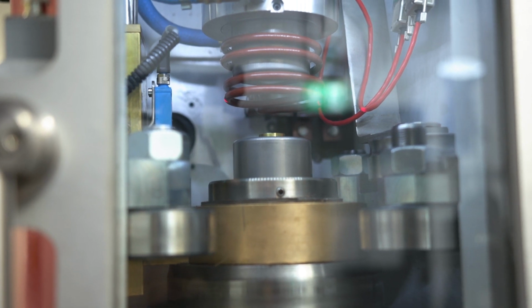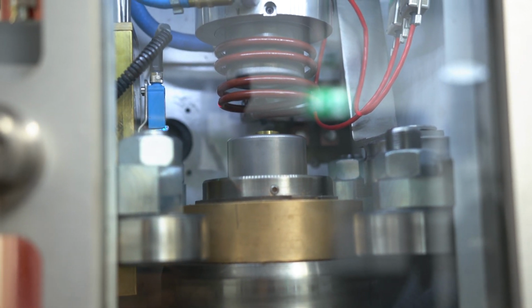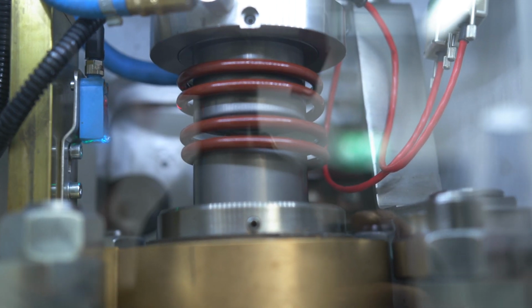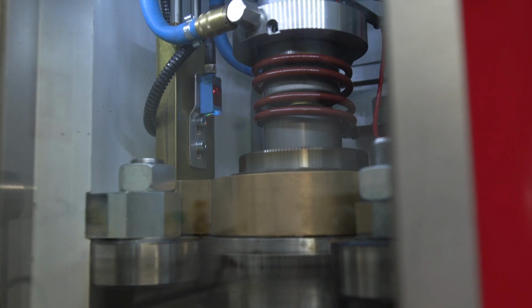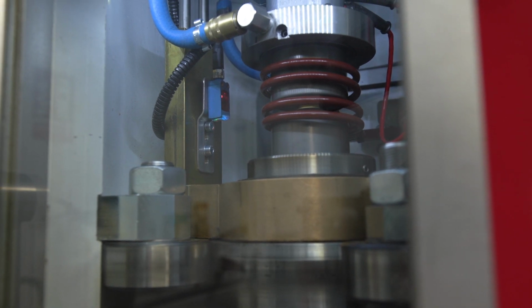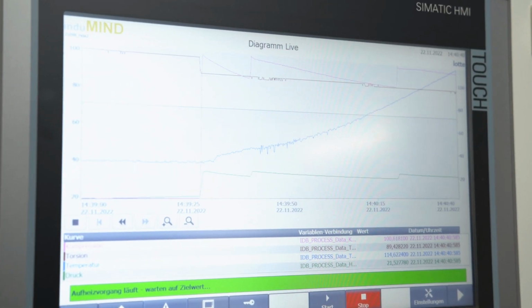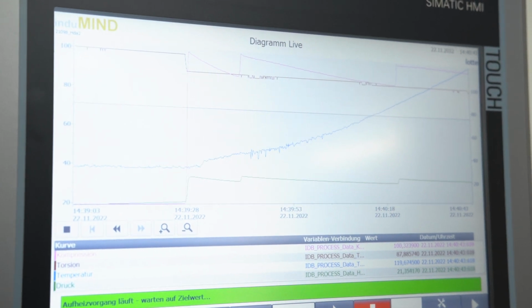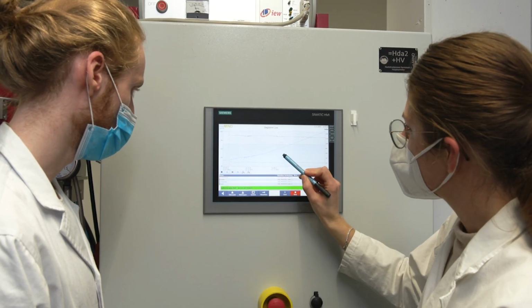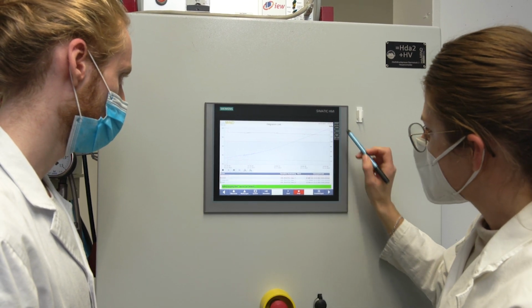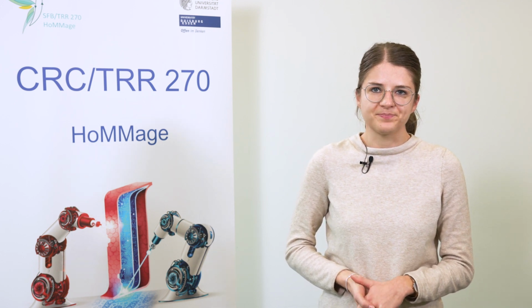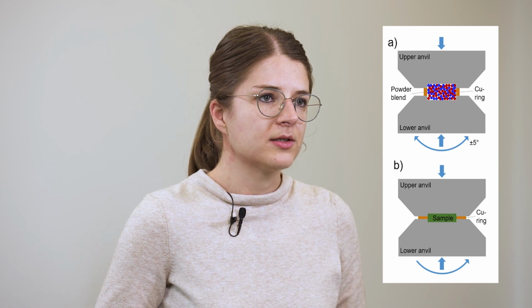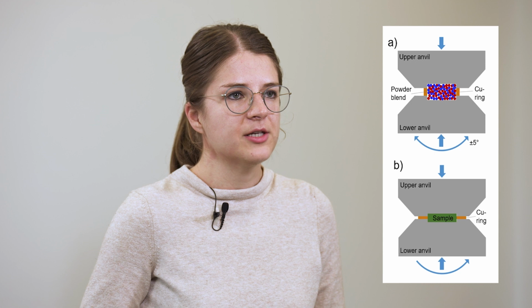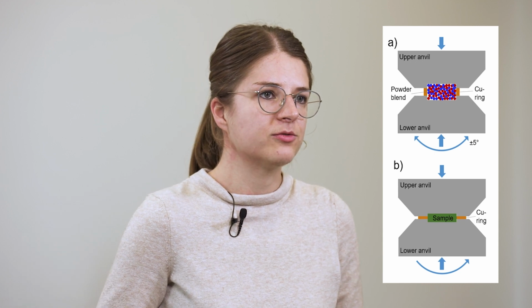During the process, we apply a pressure between 2 anvils of up to 200 tons and then simultaneously one of the anvils is rotating. And this induces a very large torsional shear strain and this leads on one hand to the consolidation of the powder and on the other hand to a grain refinement and an increase of the dislocation density and grain boundaries. And these effects are well known to affect the magnetic properties such as the coercivity. By using powder as precursors, we can go beyond the limitation of conventional production routes, since we are not limited here to phase diagrams.